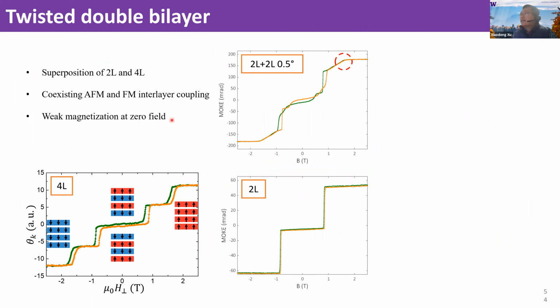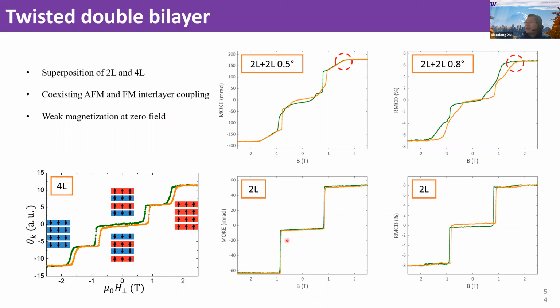The answer is no. The reason is, for bilayers, here's the data we have. We twist a bilayer on top of a bilayer. The bottom is the MCD measurement of a natural bilayer. The top is the MCD measurement of a twisted bilayer. You can see that indeed, for this twisted bilayer on bilayer, there's a little kink here corresponding to the four layers. And then in the middle, you see something which resembles the natural bilayers. And this is just two other different samples.